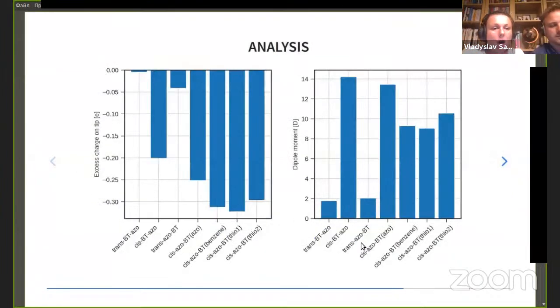Here's some data for analysis, which again shows that for trans isomers, for experimental molecule and for designed molecule, this excess charge, let's say the charge transfer between the golden tip and the organic part of the molecule, is almost 0, whereas for cis isomers, it is, let's say, substantial, up to 0.3 electron.